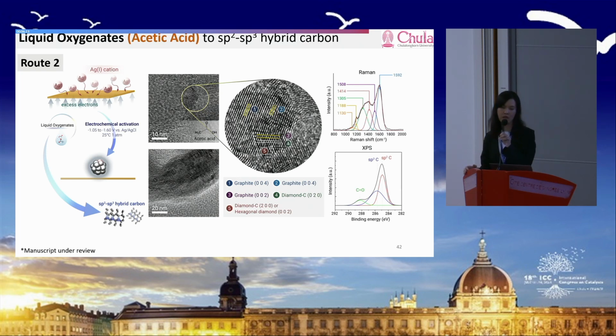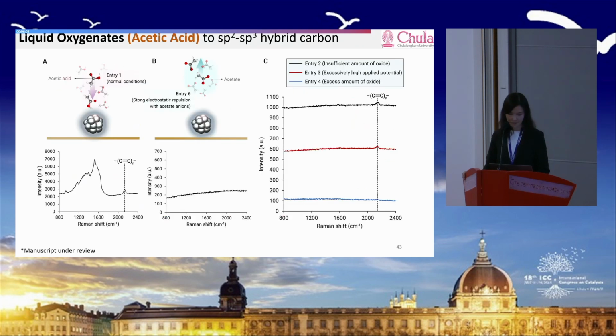So this is kind of to prove, for us as well, that there's something there doing this reaction. It's not always the case that we get a positive result. What if we have an excess amount of oxides? In the previous work we tried to make even more oxide. First we thought we wanted more active sites, something like that. But it turned out that if we have an excess amount of oxides, probably this doesn't help and even worsens the reaction